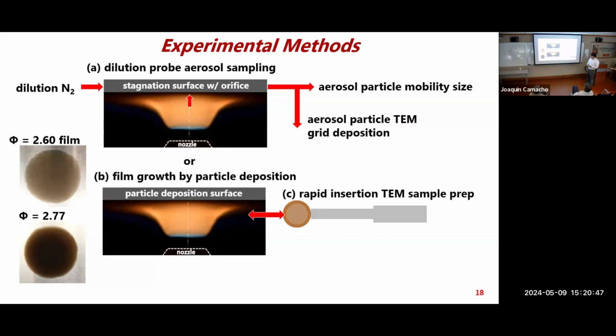Another method used to look at these soot particles is a typical very small sample holder, or sample substrate, that you put into the microscope. To get particles for the microscope, you simply rapidly insert this in and out of the flame. The relatively cold surface going into a hot flame induces a thermophoretic force, and the particles stick onto it very quickly. And you can look at the particles that stick on there.